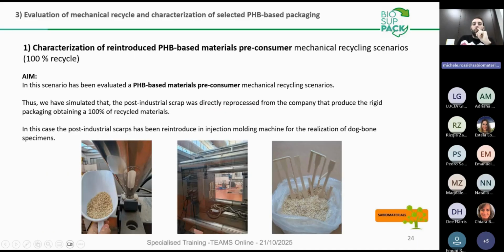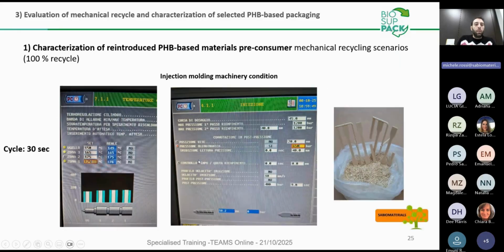So the first analysis has been the characterization of a PHB-based material, pre-consumer. So a material that will be directly reintroduced in injection molding, and the scrap could be used for the direct production of dog-bone specimens. In that case, we did the same. So we reintroduced the milled post-industrial scrap inside the injection molding, obtaining the specimens directly from the scrap, so 100% of recycled material.